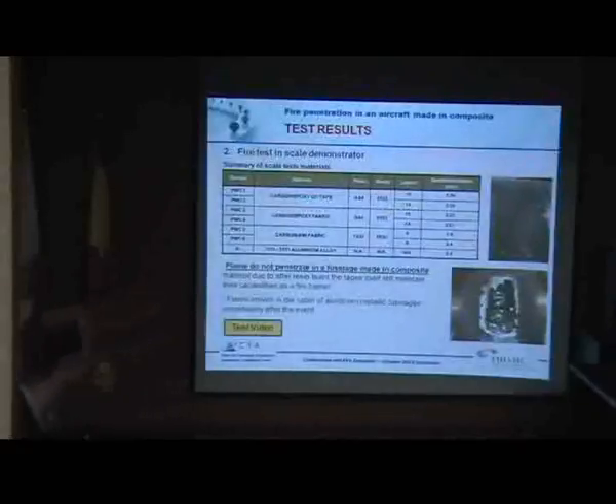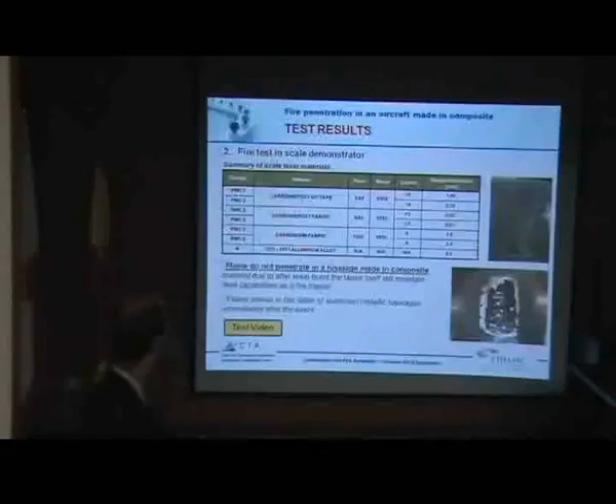And after this characterization test, we manufacture curved panels to be tested in the scale demonstrator. We test the same materials: carbon fiber with epoxy tape, carbon fiber with epoxy fabric, and carbon fiber with melamine resin. And we compare these composite materials with aeronautic aluminum alloy. So the main result we have is that the composite material avoid the penetration of the fire in the case of an external fire.